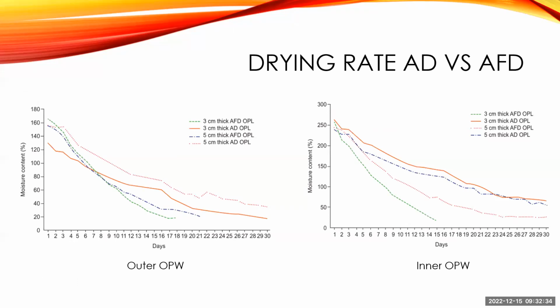This is a comparison of the drying rate between air drying and forced air drying. Using the forced air method, the inner oil palm lumber with 3 centimeter and 5 centimeter thickness could attain target moisture content of 60% at day 11 and day 16 respectively. As for outer oil palm lumber, it requires 10 days for both 3 cm and 5 cm oil palm lumber to achieve target MC of 60%.